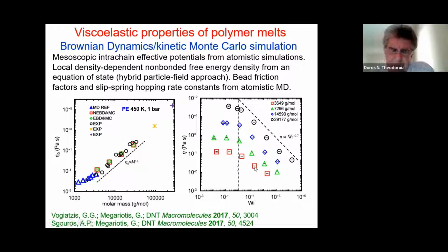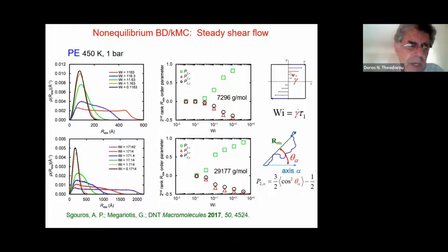However, when we have fast flows, when the Weissenberg number is very large, we see that the viscosity goes down with shear rate. We have, in other words, shear thinning. And this can be described by a power law, the power being minus 0.7 between the Weissenberg number and the viscosity. This is quite close to what experimentalists measure in these molten polymers. The mesoscopic simulation, of course, can give you what happens at the molecular level and what is responsible for this nonlinear viscoelastic behavior of the melts.